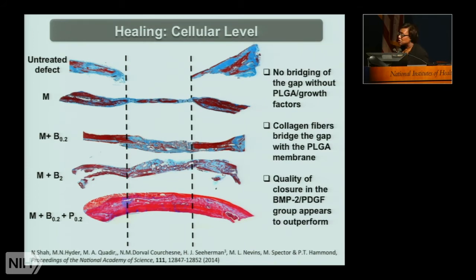If you just have a PLGA membrane and nothing else, what you get are fibroblasts, which crawl across the membrane and deposit collagen. You end up with this collagenous sort of scab-like material, but not bone. If you look at 0.2 micrograms released from our scaffold, what you can see is that you're going to get bone generated in significant amounts, certainly enough to bridge the entire defect. And all of these are taken at 4 weeks. But you also see that the bone is somewhat rough looking.